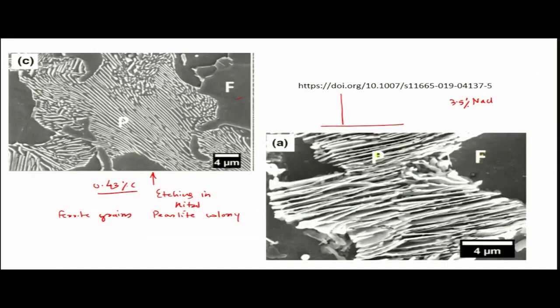This picture actually combines both the galvanic effect as well as dealloying. This is a micrograph developed after polarization — at a very high value of polarization we reached the anodic part, and after that we examined the microstructure. Remember: after polarization we have not done any etching. This particular picture has formed due to selective dissolution of ferrite.